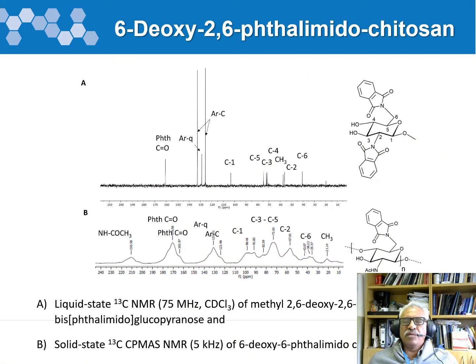In order to determine which of these carbon signals belong to the phthaloyl and which belong to the residual N-acetyl, we could do solid state NMR of the phthaloyl chitin, which is not water soluble and not soluble in many different solvents. So we do the solid state NMR, and you can see here, if you compare that with this model compound, here you can see the phthaloyl group carbon that comes up around here. It's just about 160, whereas the N-acetyl ones come up a bit higher here.